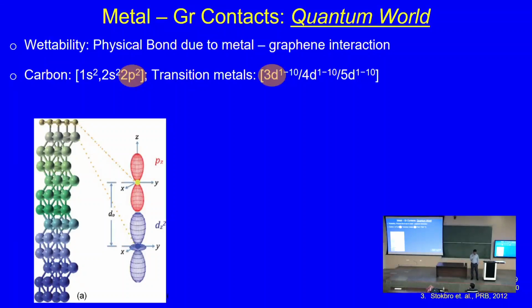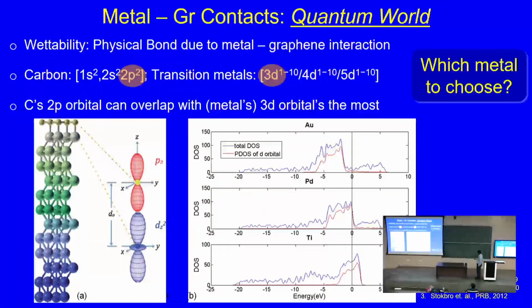And if you want to investigate chemical interaction, what will you do? You study the hybridization, right? So you have to get into the quantum chemistry of that interface, right? So that's when we started exploring the quantum chemistry of the interface, and we found that depending on the metal that you choose, a particular metal would have a certain valence state, and depending on that valence state and the number of electrons present in that valence state and the energy gap from the graphene hybridized energy state, you see some difference, some correlation in the contact resistance.